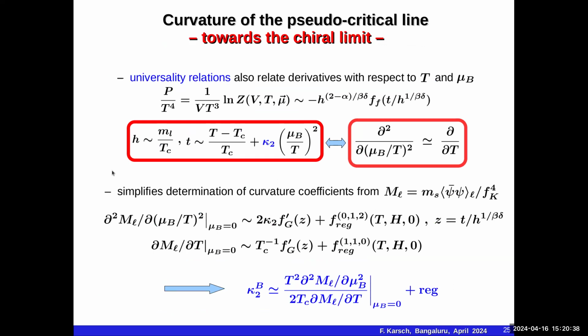In that case, the situation is a little bit easier because we again can make use of scaling properties of the QCD free energy in the vicinity of the chiral transition, and using the dependence of the singular part of the free energy or the pressure as a function of temperature and quark mass like variables, we can express the temperature like variable again as a series in terms of temperature and chemical potentials, because the chemical potentials do not break the symmetries of QCD.